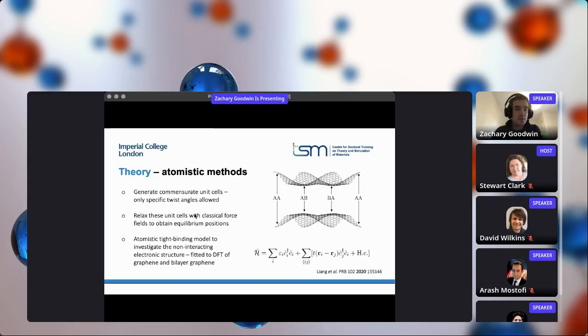And then what we do using classical force fields is relax these geometries, because as I was mentioning at the start of the talk, the stacking sequence changes throughout the Moiré unit cell. Because of this, the interlayer spacing of the graphene sheets changes throughout space quite substantially. This is a schematic and I've exaggerated the effects here, but it's just to show you the kind of effect that can happen. And this causes the formation of those band insulating states that I was mentioning. So this is really quite some essential physics to include in the model.